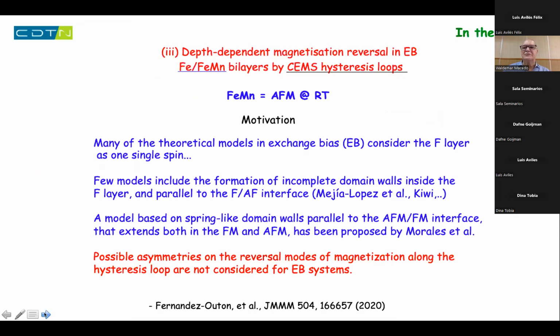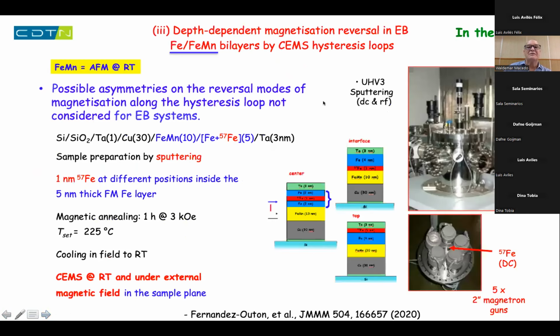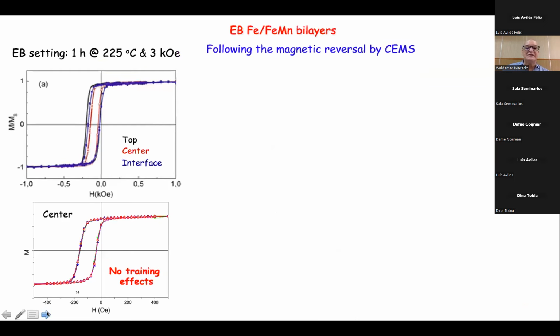And then we decided to do, it's not easy to get beam time in the synchrotron for doing Mössbauer. We decided to investigate another system where you can do a similar approach at home. What we did is we investigated iron manganese as the antiferromagnet. This is antiferromagnetic at room temperature. We prepared different samples by sputtering, placing the iron-57 at different positions relative to the antiferromagnetic iron manganese phase. And then we did conversion electron Mössbauer spectroscopy.